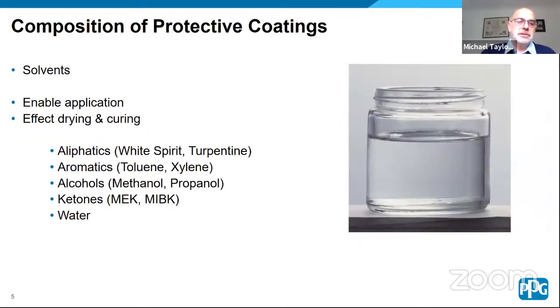Another main ingredient is the solvents. They enable the application, and they also enable us to make the paint, because obviously you have to add some solvent to get the right viscosity for the coatings to be mixed. They affect the drying and curing of the coatings. There are different types of solvents, from aliphatics, aromatics, alcohols, ketones, and now we're seeing more water being used as a solvent or diluent for coatings. It's very important that you use the correct solvent in your coatings, because they can react with the resins, and then you get different compositions that you don't want in the coating and get adverse reactions.